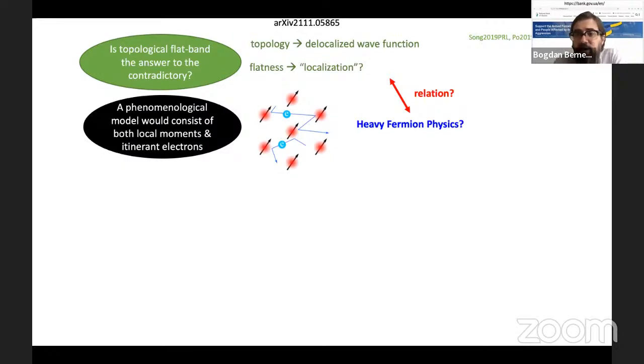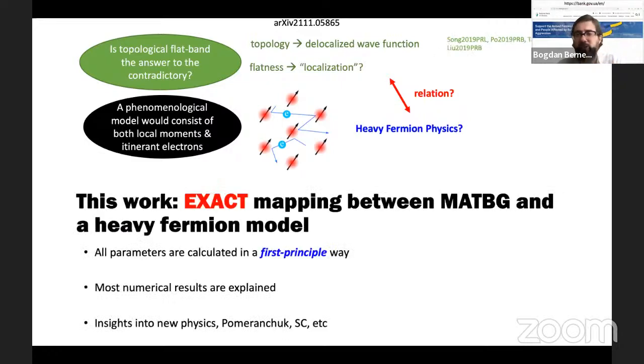Now, the heavy fermion physics would have to, again, contain some heavy elements, which we'll call f-electrons, which don't really, there's nothing, all graphene is p orbitals, carbon p orbitals, really, just a huge amount of them. But we're going to call these made up heavy elements f-electrons, and some c-electrons, which are some conduction electrons, some itinerant electrons. And this juxtaposition, if we find it, should explain some of these contradictory pictures. Now, what we actually found was an exact mapping between the twisted bilayer graphene, and I'll show you trilayers and multilayers.